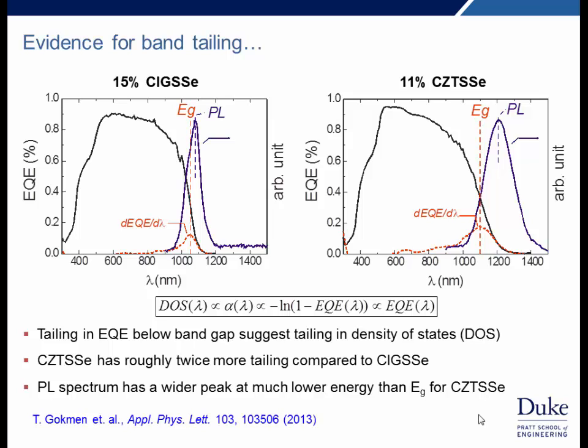As far as evidence for band tailing in the materials, we can look at the quantum efficiency. Quantum efficiency in the long wavelength regime is proportional to the absorption coefficient, which is in turn proportional to the density of states. So tailing in the quantum efficiency is proportional to the density of states. And if we compare a CIGS-based device with CZTS, we can see that the tailing, or the cutoff of the quantum efficiency at the band gap, is much shallower in CZTS compared to CIGS.